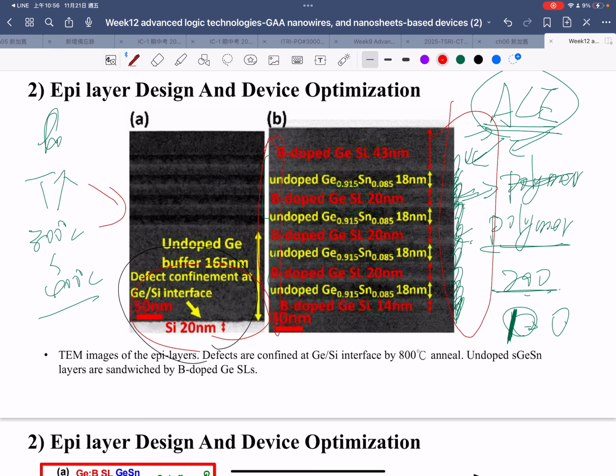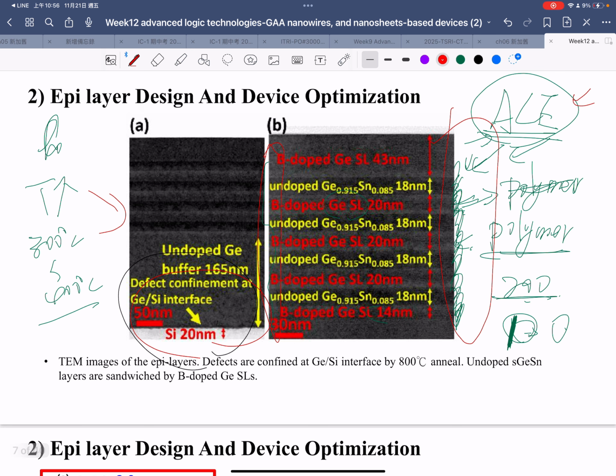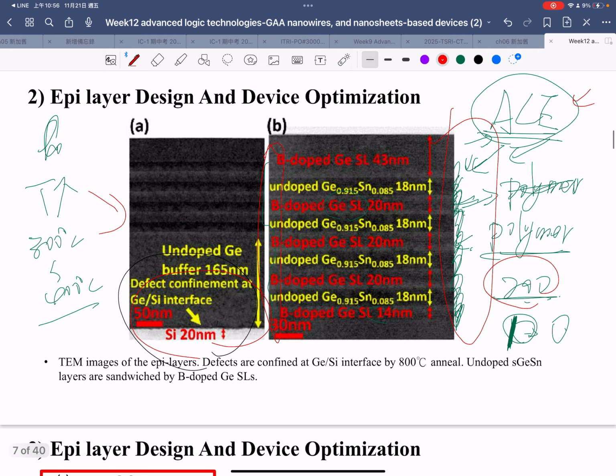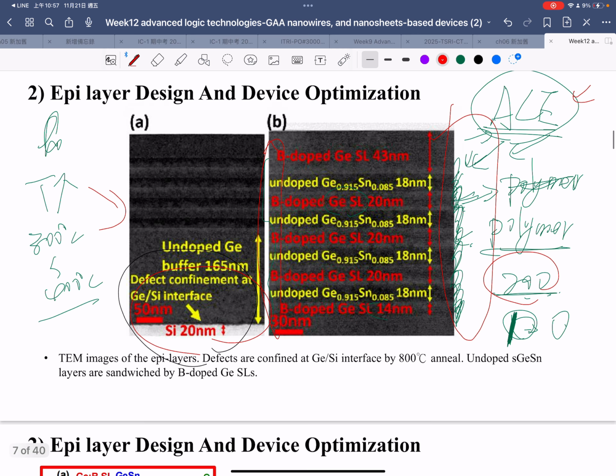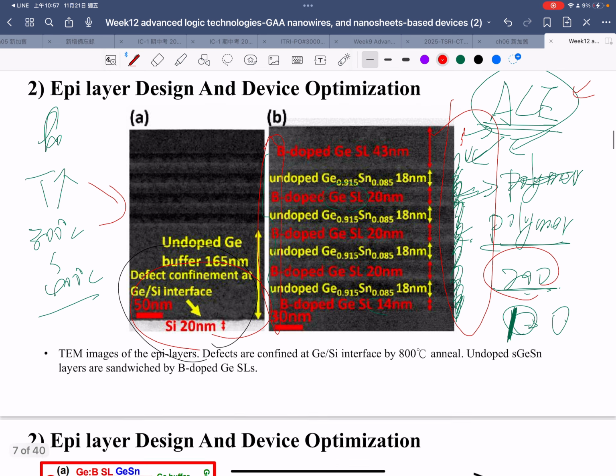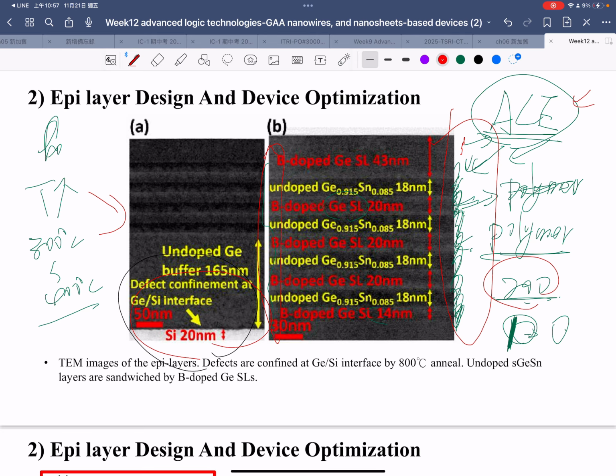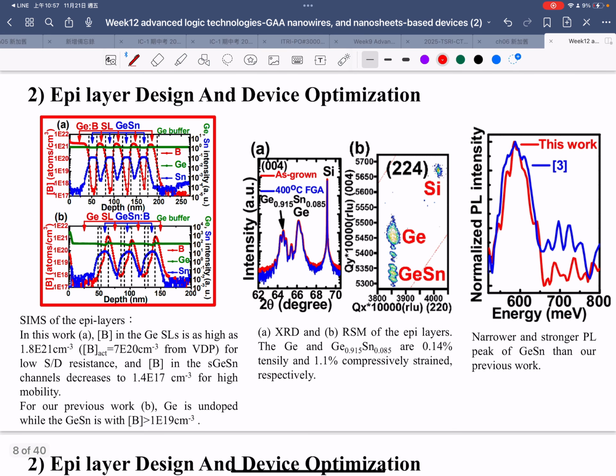So usually we use a test wafer to check the etching selectivity, which is good. The etching selectivity is larger than 200. So we are so happy, and then we load the product coupon wafer for ourselves, and after 10 minutes, oh my God, nothing happened. Actually, we have no idea what happened. Why nothing happened? Okay, so the polymer is a tricky layer. During the isotropic etching, you have to remove the polymer first.